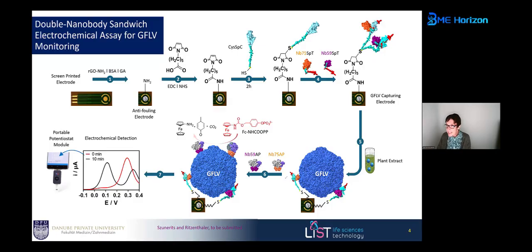So what we opted for in this case is a sandwich assay. And the sandwich assay is very easy with a virus because a virus is like a sphere. That means the ligands which are not attached to the interface are still present. So we can allow ourselves to attach again two different nanobodies, but this time modified with an enzyme, alkaline phosphatase, on the interface. And for the chemists among you, we tried to use a probably novel and more interesting redox label to read off the presence of the alkaline phosphatase. What you do normally with alkaline phosphatase, you need redox labels which are sensitive to the presence of the alkaline phosphatase. But the issue is often that the redox peak of the product is much, much more anodic than the initial interface.